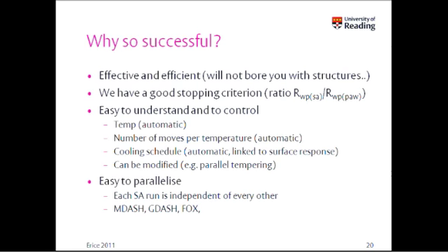Why is it so successful? Well, one is that it's a very powerful algorithm, so we'll get that out of the way. Why has it been so successful in the context of powder diffraction? Well, we have a good stopping criterion. We know when we're getting close to the answer because we will have an Rwp value, a fit value, from this model-independent profile fit that I mentioned. And if the simulated annealing Rwp is very close to that, some small multiple, say 3 or 4, of the best value that we could hope for, then we pretty much know that we have the answer.